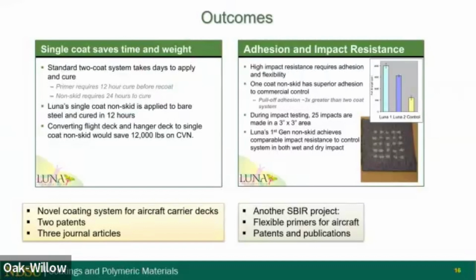We also met or exceeded all of the properties you needed for a non-skid deck coating, which are really pretty severe, and met all the weathering requirements. And so, again, very successful project. I wish we had been able to get this in the testing actually on a ship, but there's always a lot of hurdles with the government and getting that to happen. But we ended up with a novel system. We had 2 patents issue out of this and 3 journal articles that we were able to publish. So again, successful. That led into another SBIR project that we did for flexible primers for aircraft.